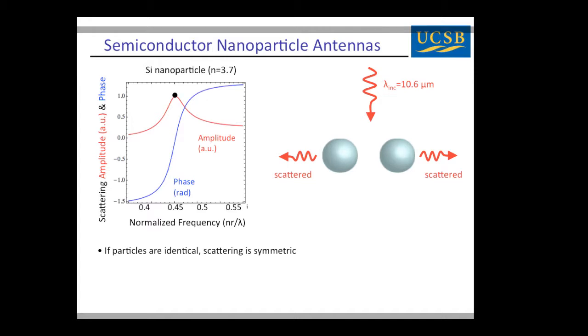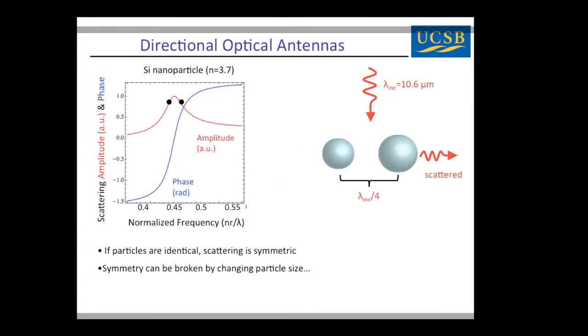And I put this black dot on the screen to show the idea that maybe we design their sizes to be at peak resonance. So how would we make a directional lobe? Well, we need to break symmetry. So the idea here is we can have two different size particles. One is larger than the other. So now we have two black dots. They are equal in amplitude, but one is detuned to lower frequency and one to higher frequency.